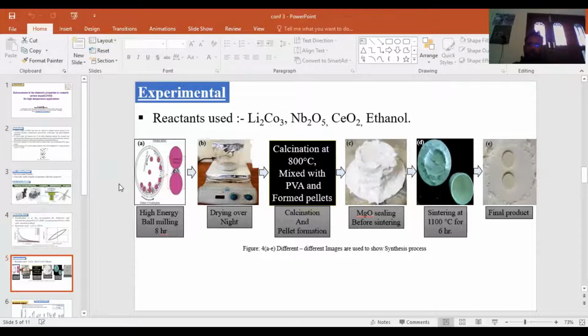Now the experimental part of my research work. For the experimental part, I have used lithium carbonate, niobium pentoxide, and cerium oxide as reactants, and also used ethanol as the wet medium. In figure 4a to e, I try to show my research work with the help of images. In figure a, I have shown the ball milling process. I used a high energy ball mill for 8 hours, where I used ethanol as a wet medium.